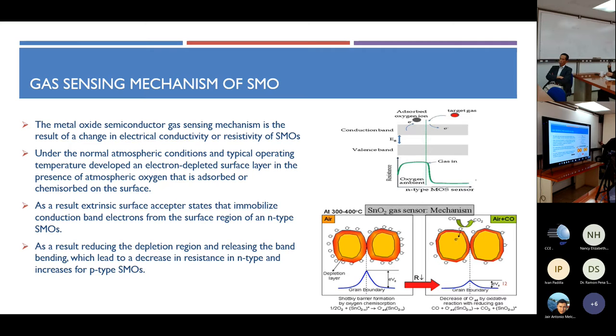This graph shows the resistance change. In the same case, when the target gas interacts with the material, desorption takes place and electrons are injected back into the material, where the electron flow happens. The space charge layer decreases, and because of the decrease the Schottky barrier is reduced, so the resistance decreases further, the conductivity increases, and there is a flow of electrons.